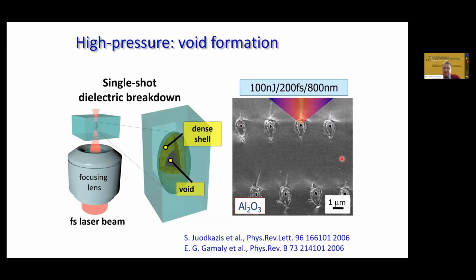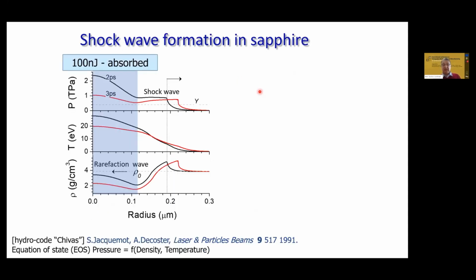If we see what is inside those modified regions, by simply breaking the sample in half, you can see that it's a pinched hole with a modified region around, and this cone corresponds to the focusing cone of light. Each pulse makes a single damage. You see the conditions: the energy of the pulses, the energy coming onto the sample, is quite small, but the focusing is very tight.